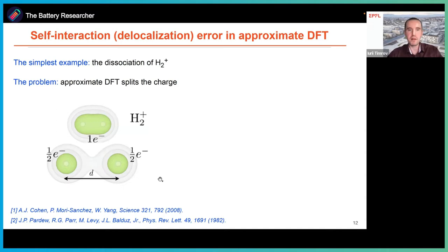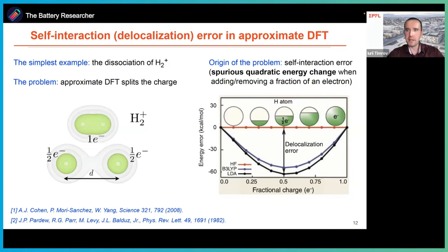Now, the origin of the problem is, as I said, the self-interaction error, or in other words, the quadraticity of the energy. When we are adding a fraction of an electron to the ion, the energy changes quadratically, as you can see here. But in reality, it must be linear. This quadratic behavior is unphysical and spurious, and it is due to the self-interaction errors. Because of this problem, if we try to use DFT with simple approximations to exchange correlation functionals, we obtain unreliable results. So we need better methods that would allow us to somehow alleviate these self-interaction errors.